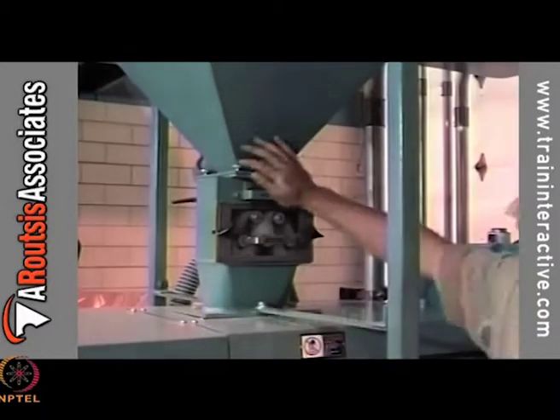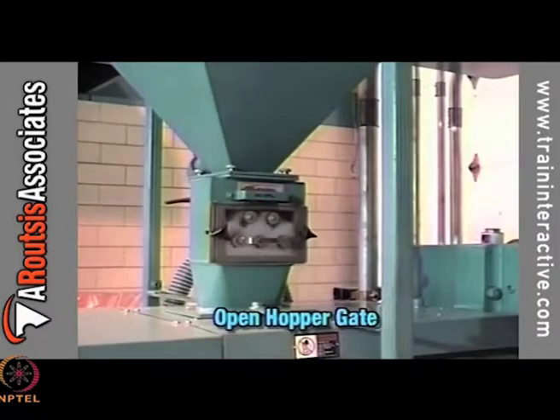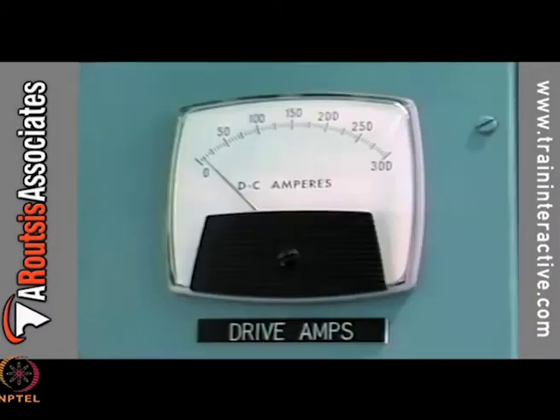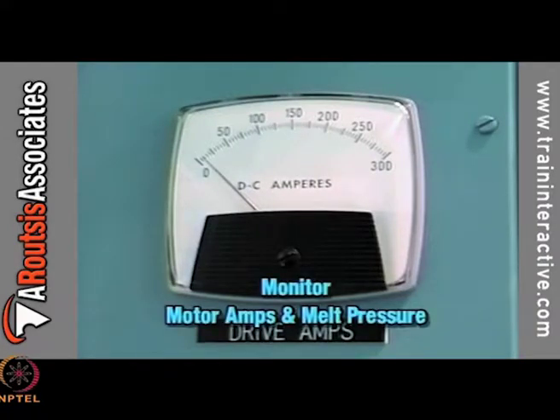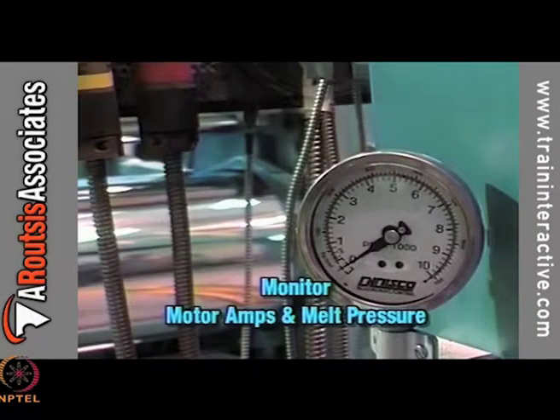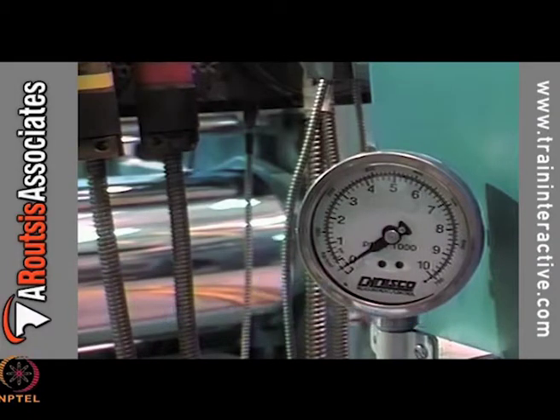In compounding, start only the main polymer feed. Don't let the extruder run empty for more than a short time because it causes rapid wear on the screws. As plastic flows into the extruder, watch the drive amps or percent load as well as the melt pressure gauge. If either one exceeds the normal startup value, find out why. Do not let it go because there may be a problem.